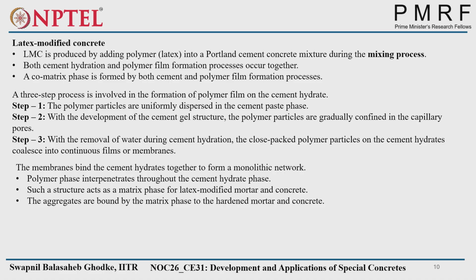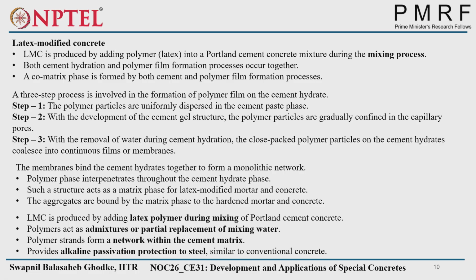The membrane binds the cement hydrates together to form a monolithic network. As both the reactions occur together, it should form the monolithic network to get the intact property of the latex modified concrete. So polymer phase interpenetrates throughout the cement hydrate phase. Such structure acts as a matrix phase for latex modified mortar and concrete. The aggregates are bound by matrix phase to the hardened mortar and concrete.